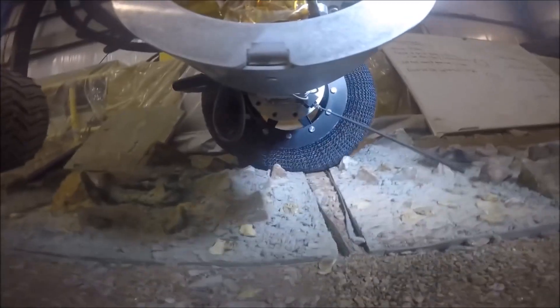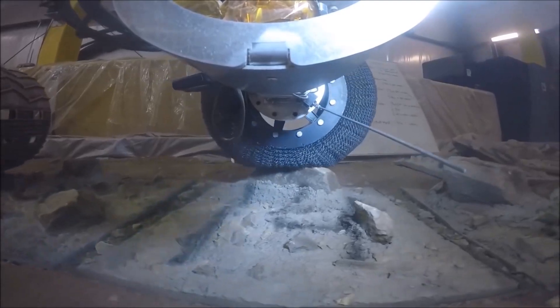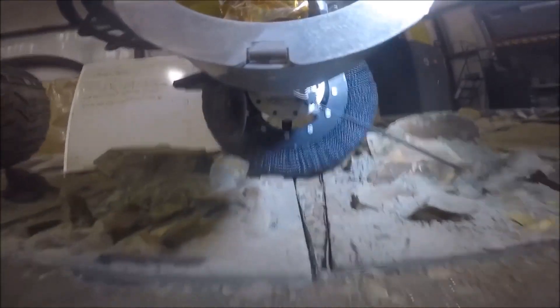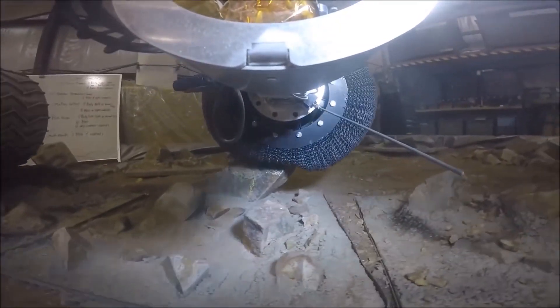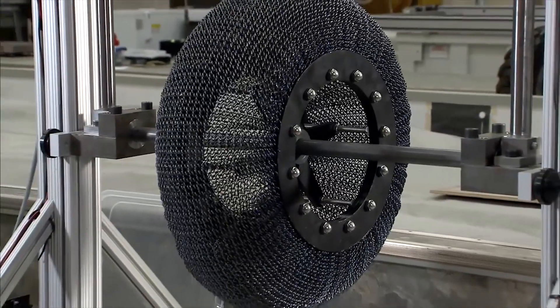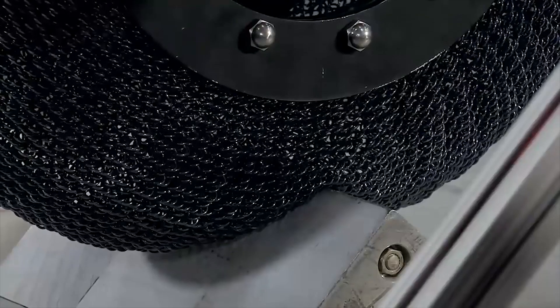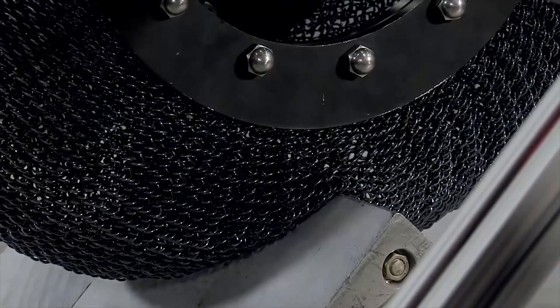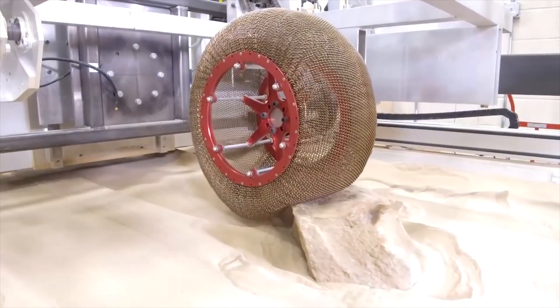So how is this useful for the Mars rover? Do we have to apply heat to the metal so it can recover its shape after running over a particularly big rock? No — luckily, Nitinol can be induced into that martensite-to-austenite transformation through stress and strain. When the stress passes a threshold it causes the crystal lattice to transform to austenite, and when the stress is released it returns to martensite and the metal recovers its shape. This is called superelasticity, and it is the property that allows these new Mars rover wheels to deform right down to the rim and still recover their shape. This combined with the interlocking coil design allows the tyre to tolerate strains in a way no other tyre could, while surviving the harsh Martian environment.